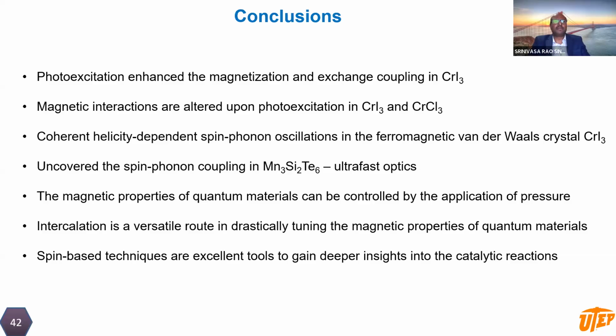And out of all, we find that intercalation is a very versatile, easy route to drastically change the magnetic properties of these layered quantum materials. And one can enhance the Curie temperature from 150 Kelvin to 350 Kelvin, and one can induce new magnetic phases on these layered quantum materials, using simple non-magnetic organic intercalation like TBA plus. So currently we are expanding this work to sodium, potassium, rubidium, etc.